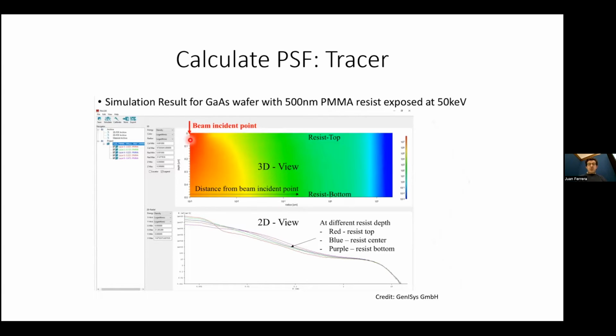This is where the beam impinges, and you can see how the energy is being deposited. Let me point out that the radial scale here, this is the radius in microns, and down here is logarithmic, and also the exposure here is logarithmic. But you can see how there's a backscatter. This, by the way, is a gallium arsenide wafer with 500 nanometers of PMMA exposed at 50 kilo electron volts. And you can see the beam being forward scattered, and you can see this green area is where the backscattering is taking place.